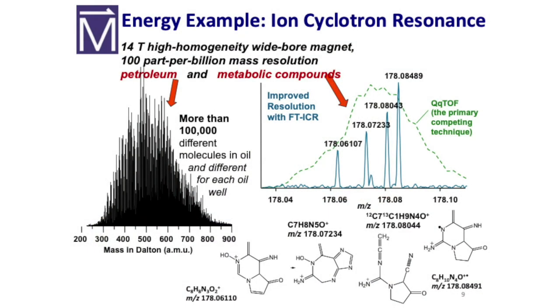So here's an example of the plot you get. Just in a few mass Daltons, we find more than 100,000 different molecules in oil. And this is used a lot for oil. If you compare to the competing technique, which is time of flight spectroscopy, what we find is that this is much, much higher resolution. So what can you do with this?